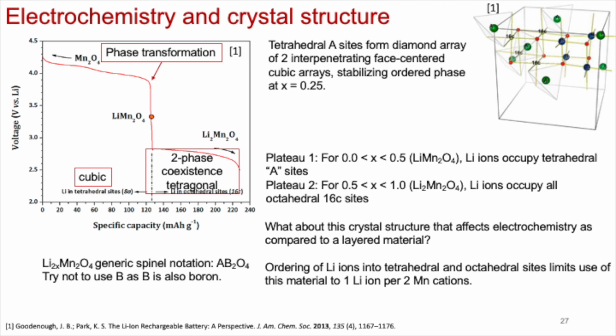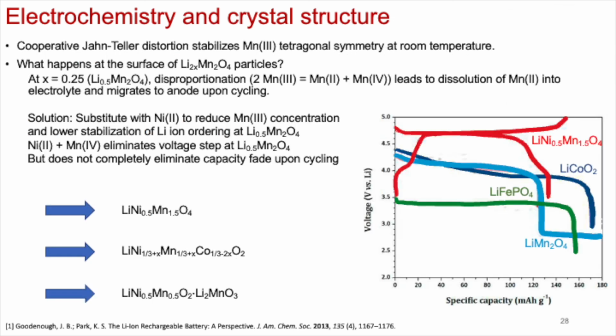So I'm just going to wrap up, but I'll continue because I want to make a specific point, which is, we can understand that manganese 3 is unstable in the tetragonal symmetry, but we can say, okay, if manganese 3 disproportionates into manganese 2 and manganese 4, is there another transition metal in the 2+ state that we can use to stabilize it? So we can basically reduce the amount of manganese 3 content in the spinel structure.